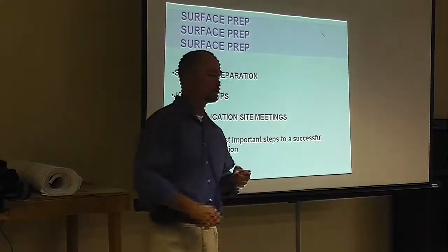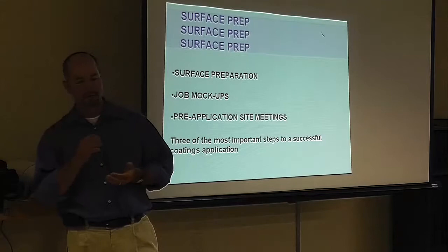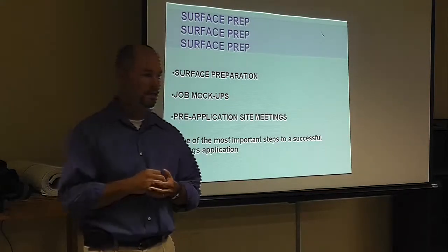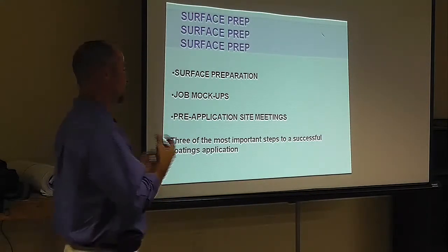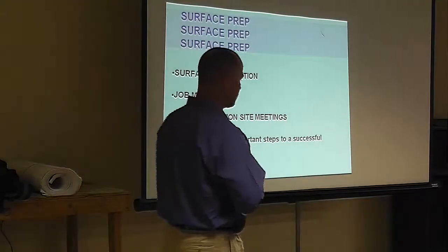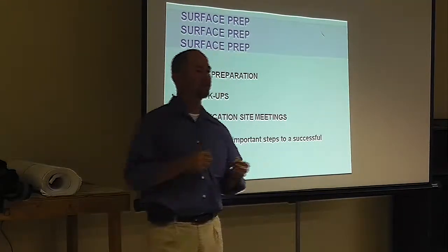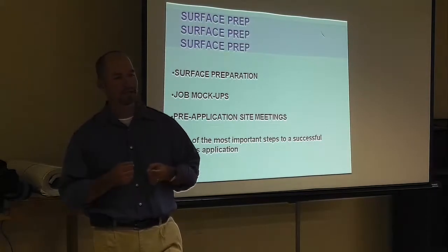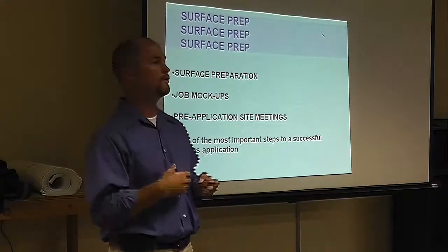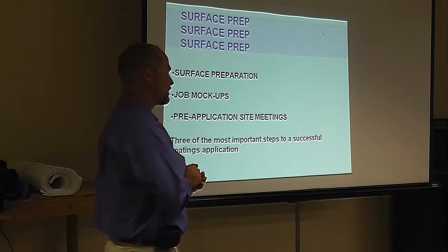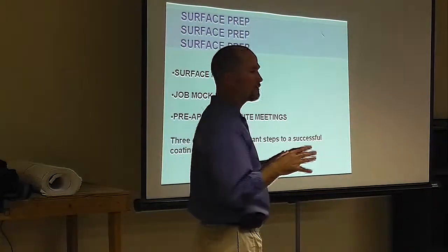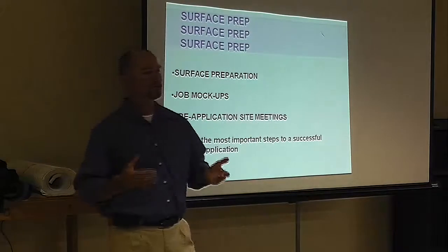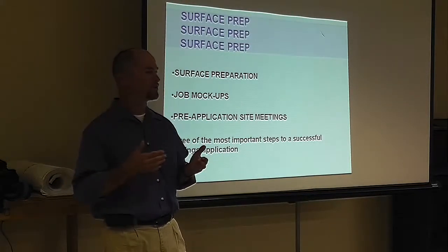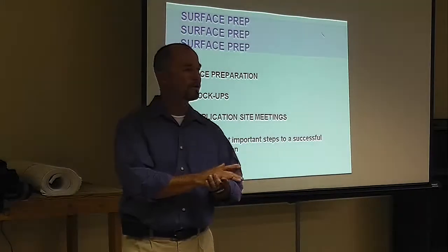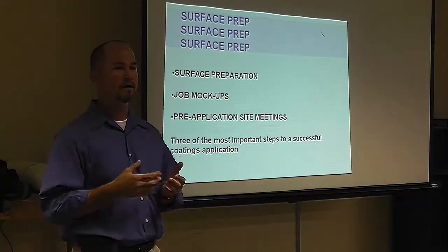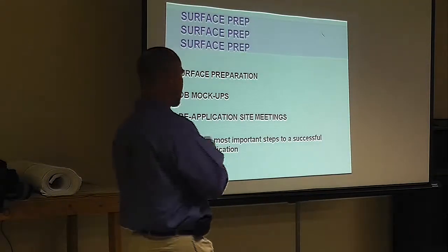One thing that's critical, the most critical thing with any type of coating application, is surface prep. With contaminated substrates, if you're doing a recoat on a building downtown Dallas, exhaust fume is a contaminant. So a lot of times you need to do a light degrease and clean and light pressure wash. If you're coating CMU block or split face block, I like to see a very light wash, because you don't want to introduce more moisture. At 3,000 PSI, you can push a hell of a lot of water into CMU block. If you come back and put a coating on it too soon, you've just sealed moisture inside that block, so you're going to have some issues. So we like to see a light application.